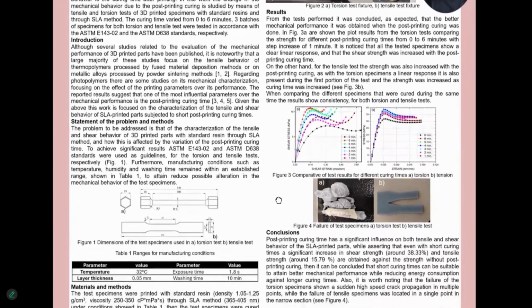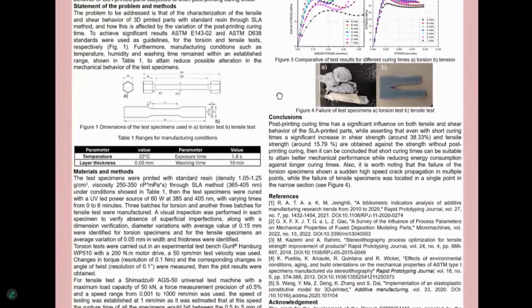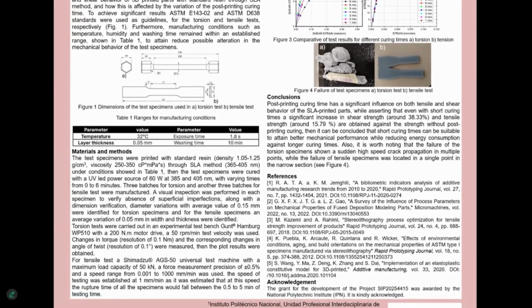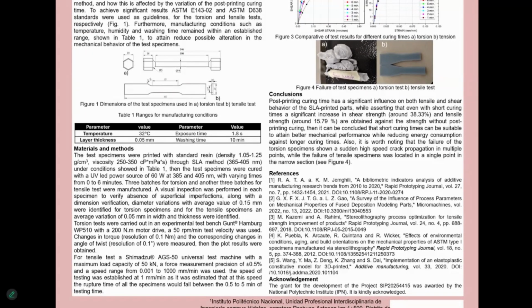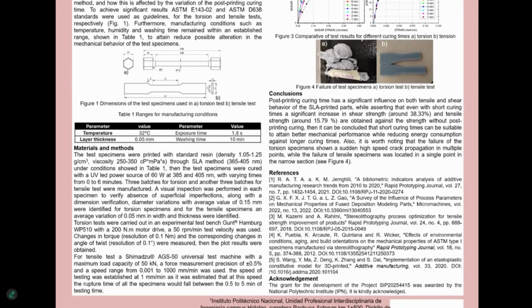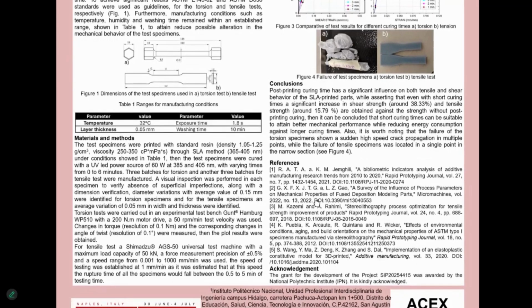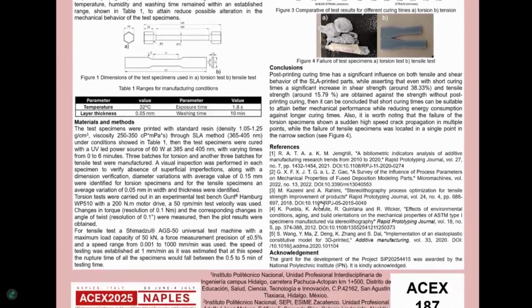Given this, the problem to be addressed in this work was the characterization of the tensile and shear behavior of 3D printed parts with standard resin through a stereolithography method, and how this is affected by the variation of the post-printing curing time. For this work, we built 42 test specimens with standard resin through the SLA method under conditions of controlled temperature, washing time, and post-curing time. The post-curing was done through a UV LED power source of 60 watts at 405 nanometers with varying times from 0 to 6 minutes.